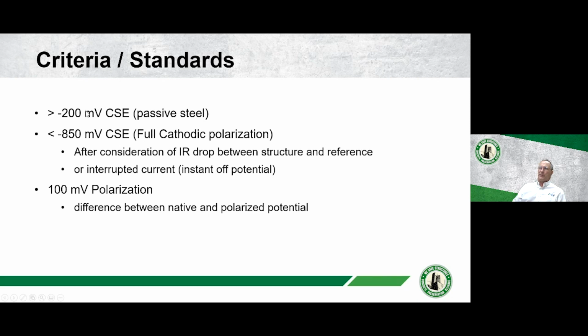If the potential of the reinforcement is more positive than minus 200, the steel is passive, so you don't need cathodic protection. If the potential of the steel is more negative than minus 850 millivolts, you have achieved full cathodic polarization, which means there's no corrosion activity, and you've consumed the oxygen that's available at the cathode, so no corrosion can occur in that environment.